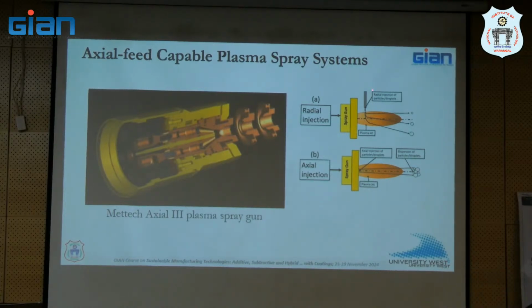The other is if you introduce it radially, the powder behaves in a very different way. It behaves crazy. If your powder particle size is fine, it just doesn't go in the center. It bounces off. Because at that temperature, what's the plasma temperature? I showed you. How high is the temperature? 15,000 degrees, right? So at that temperature, the gas is very viscous. The viscosity of the plasma plume is huge. So if you have fine particles, they cannot penetrate the plume because of the viscosity.